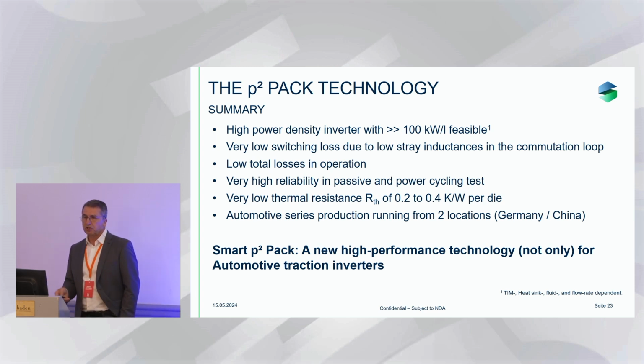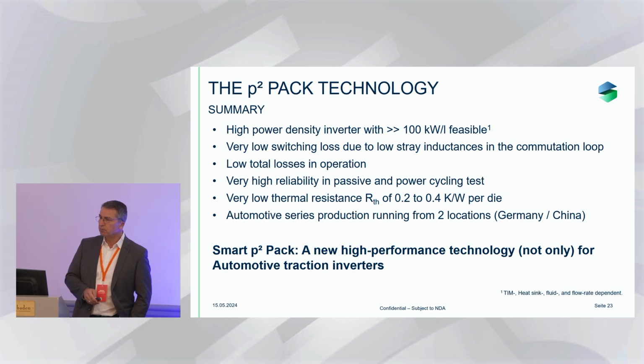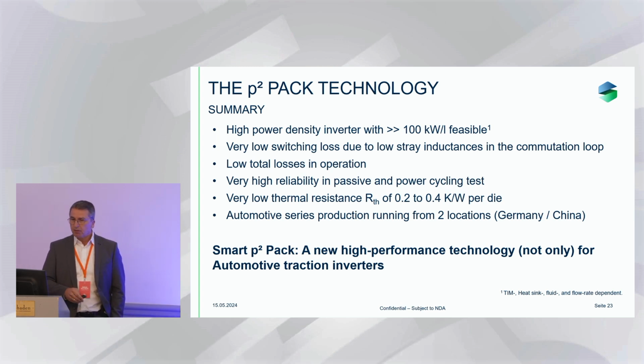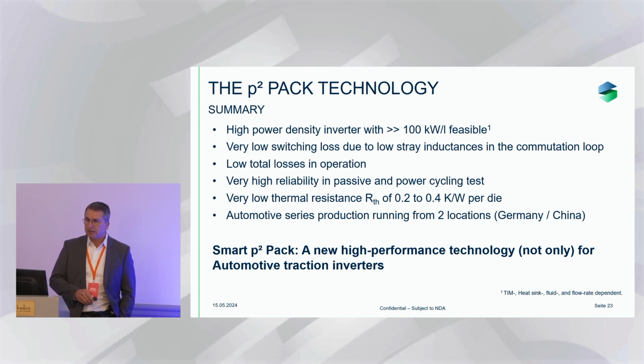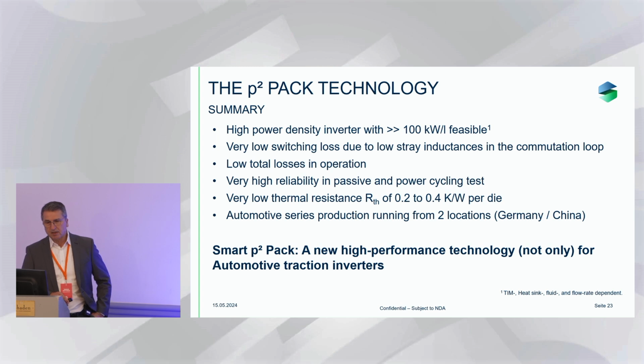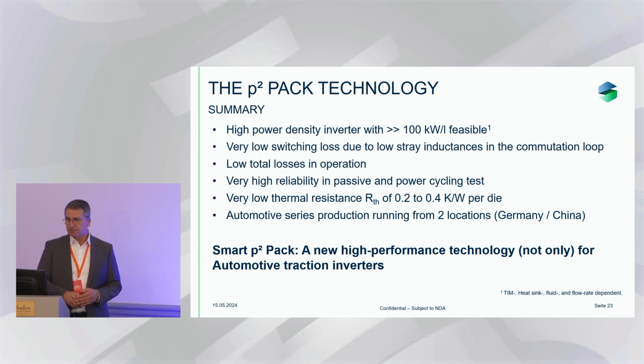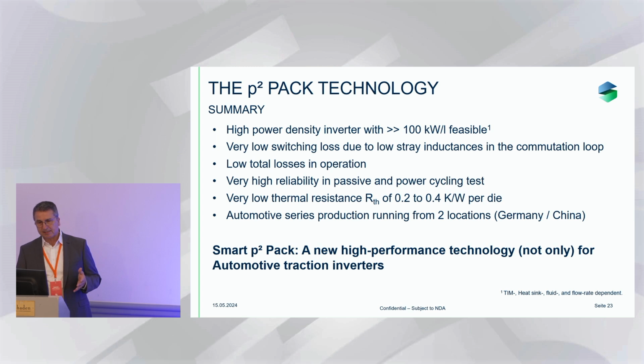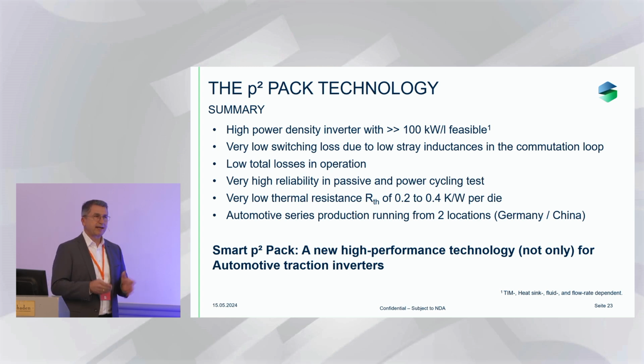I showed you that you can achieve a high power density inverter with much more than 100 kilowatts per liter. We have very low switching loss and very low stray inductances in the commutation loop, and we see very low total losses in operation. So we have a very high reliability as well in passive and in active power cycling, and there is a very low thermal resistance of 0.2 to 0.4 per die, and we already have an automotive series production running from 2 locations, one in Germany, the other one in China. So we think this is a nice new high performance technology for automotive traction inverters and other applications.